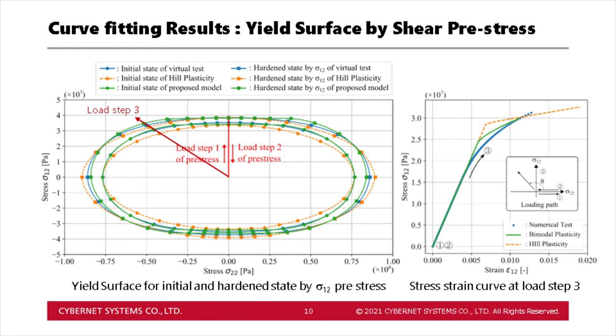Now, I will show the results of curve fitting the virtual test results using this material model. First, I show the case where shear pre-stress is applied. The left side shows the yield surface. In addition to the results of virtual test and response of the proposed model, the results of the classical Hill's model are also given for reference. The colors blue, orange, and green represent the results of virtual test, Hill's model, and our proposed model respectively. And the circular plot shows the initial state, and the square plot shows the post-yield state.